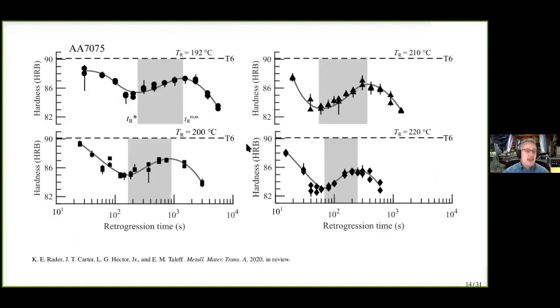So if we begin looking at hardness, this is room temperature hardness as a function of retrogression time at several temperatures. So we start out here at 192 Celsius, 200 degrees Celsius, a little bit higher temperature. Now, why 192? Because we did all these experiments in salt pots so we could rapidly heat and then rapidly cool the specimens. Great for scientific studies. And our salt will begin to solidify right under 192 Celsius. So it's a practical reason for the lower bound of the temperatures we investigated.